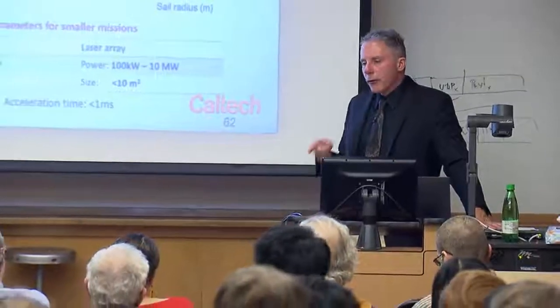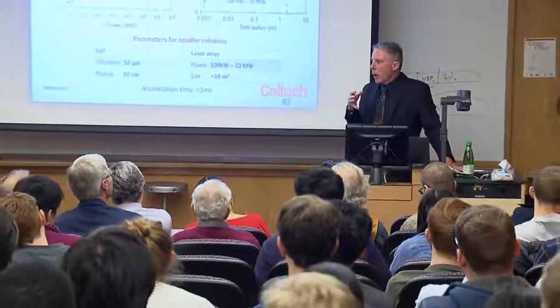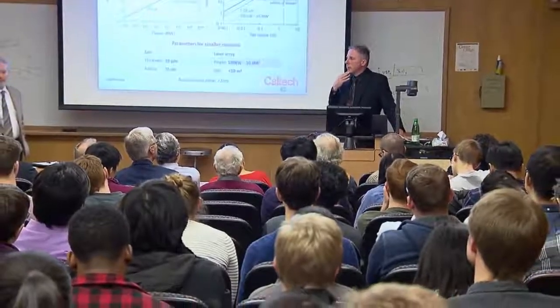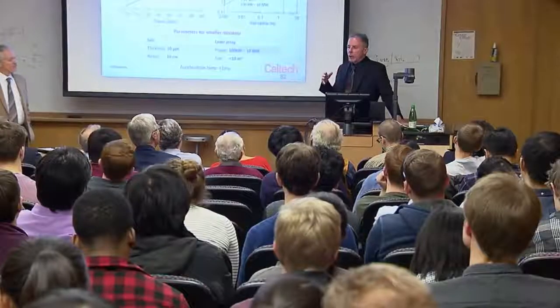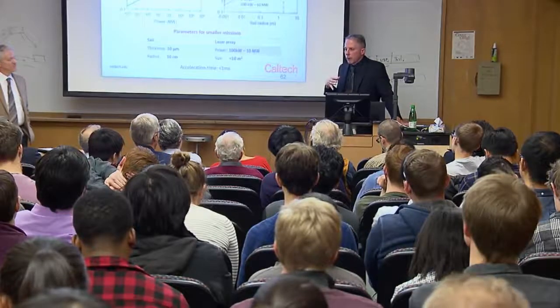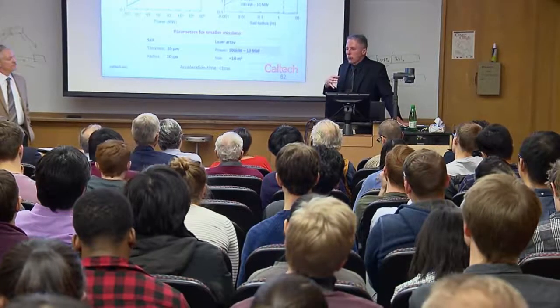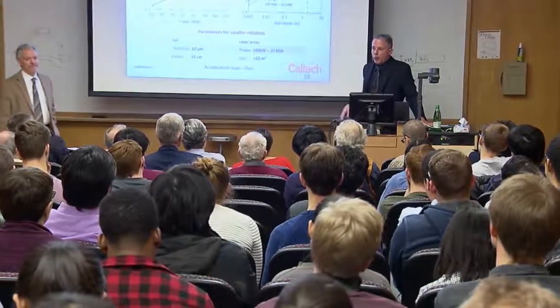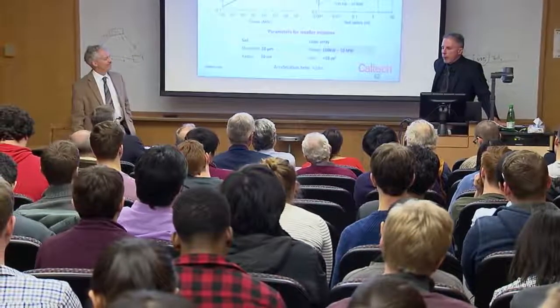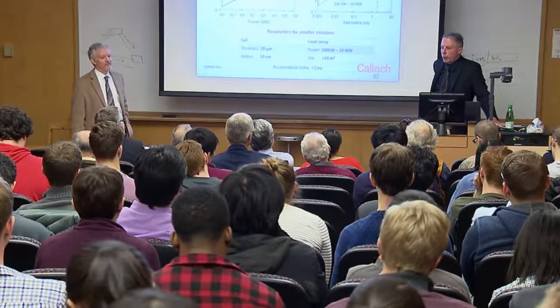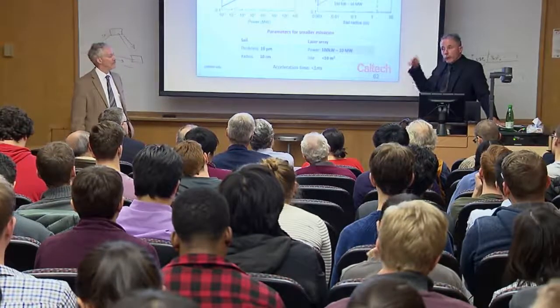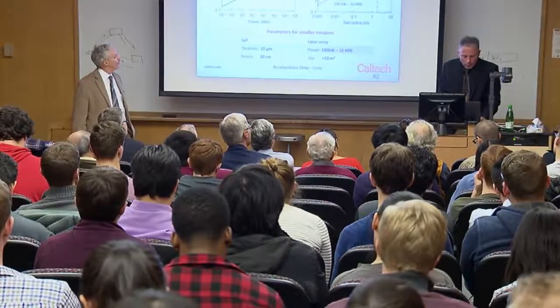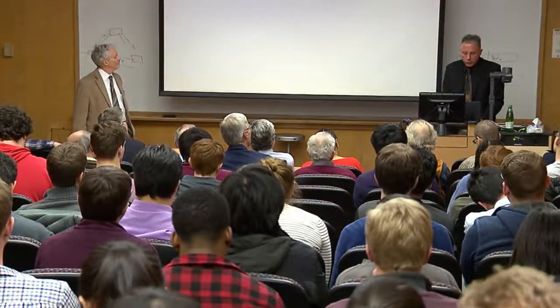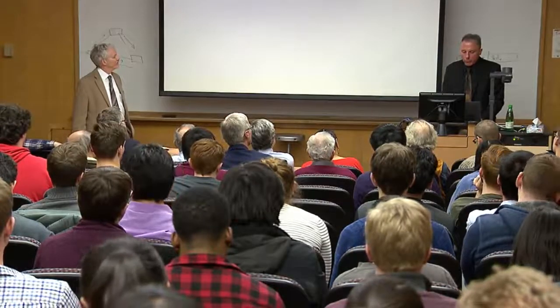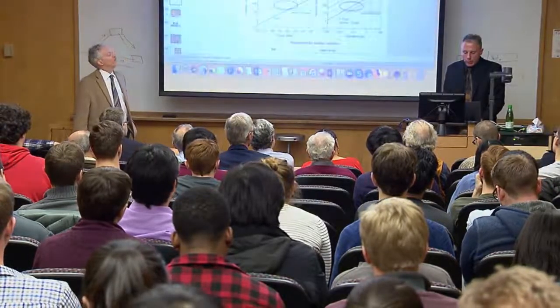So I should say that the consequences of doing that for the mechanical properties haven't been analyzed. So whether that's going to end up, and that's important, there's a lot of work to do here. This is very much the beginning rather than the end of the story. And the sizes of those were roughly what the pores were? They're in the range of a few hundreds of nanometers, something like that. So they're relatively small. They're wavelength scale, within the silicon.